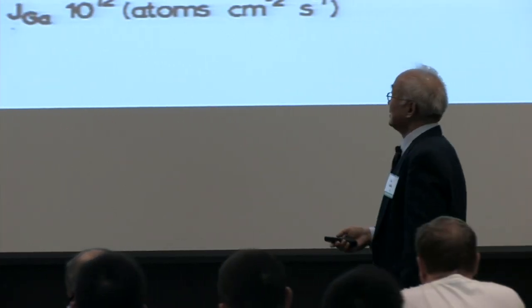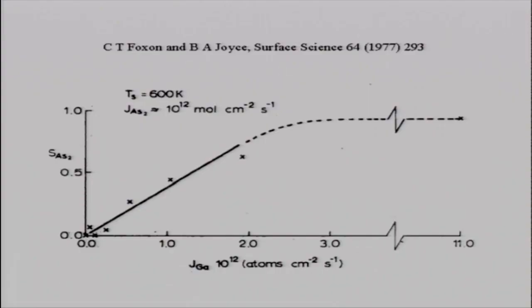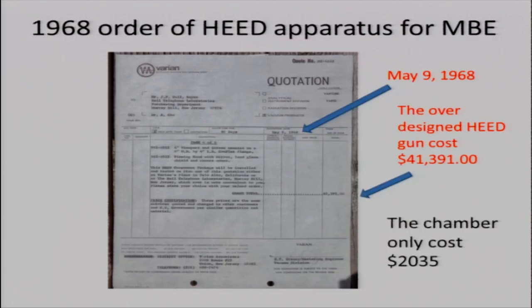And Tom Foxon and Bruce Joyce also did the experiment that he's plotting here, the sticking coefficient of arsenic as a function of gallium beam arrival rate. Again, when the gallium beam arrived at a higher rate, the sticking coefficient of arsenic increased. That was published in 1977.